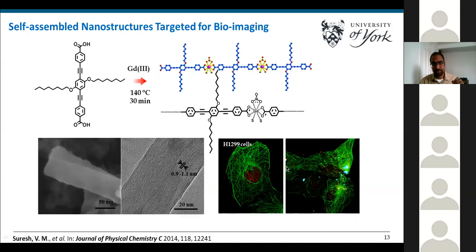We have extended this OPE-based system to optical imaging applications. So we have used the same OPE linker, but changed the metal ion from zinc to gadolinium ion. In this case, we see formation of a rod-like nanostructure, but here also we see a continuous line-like structure with a spacing of 0.9 to 1.1 nanometer. So we would expect a similar packing in the case of the gadolinium nanorod as well. And since they are inherently fluorescent because of the linker, we have used them for cell imaging applications.